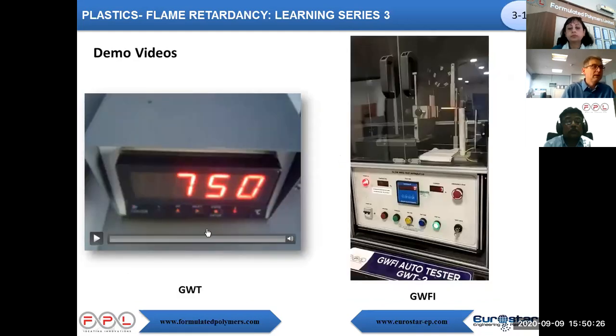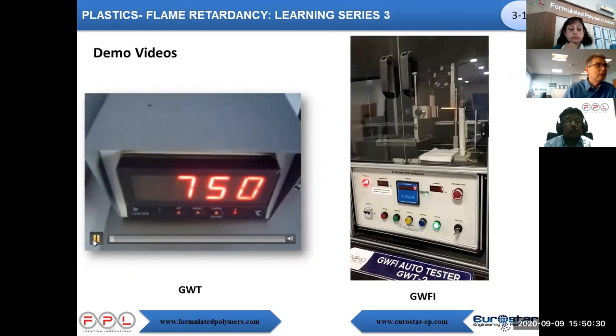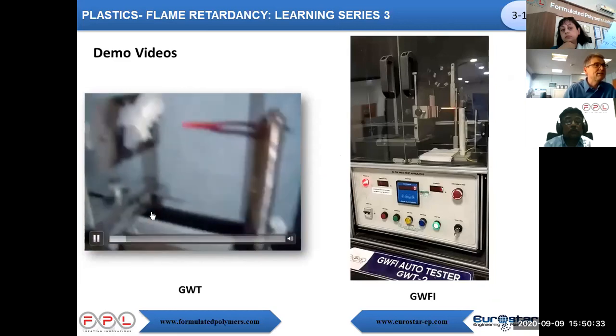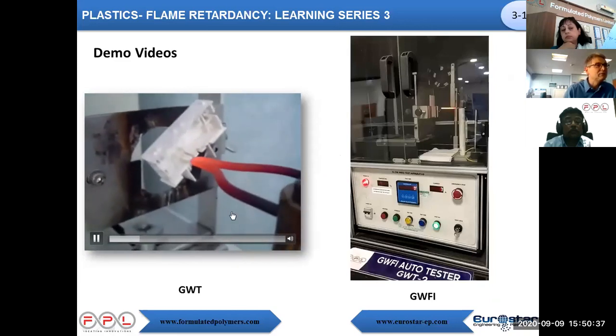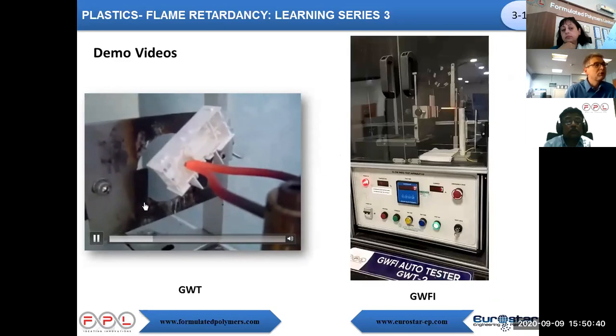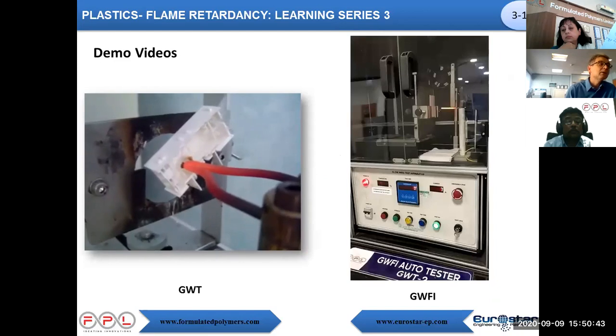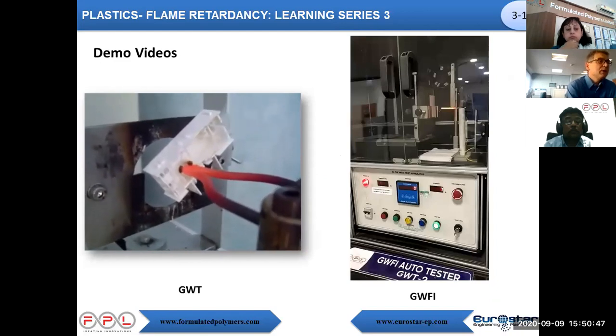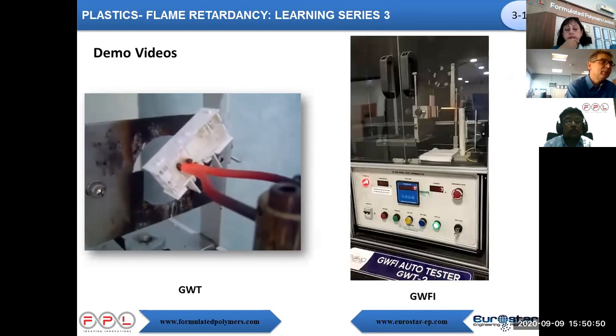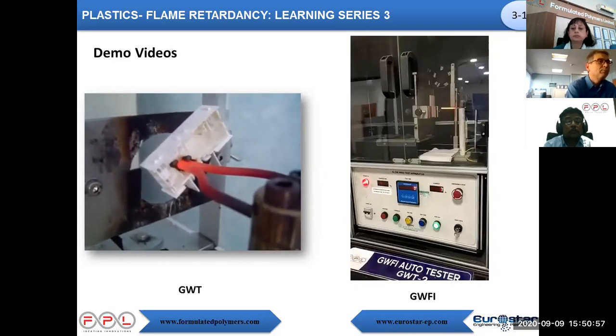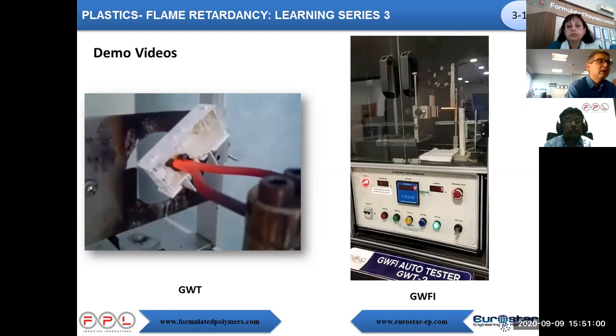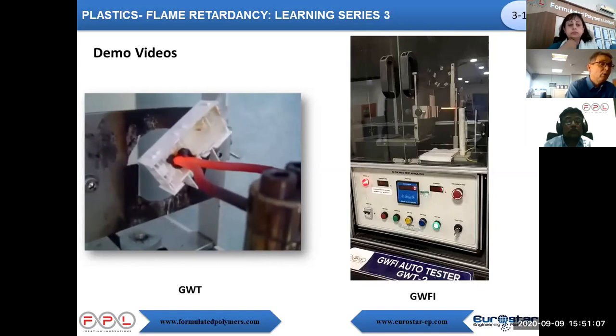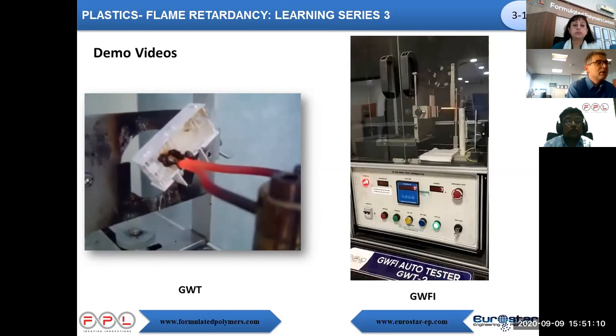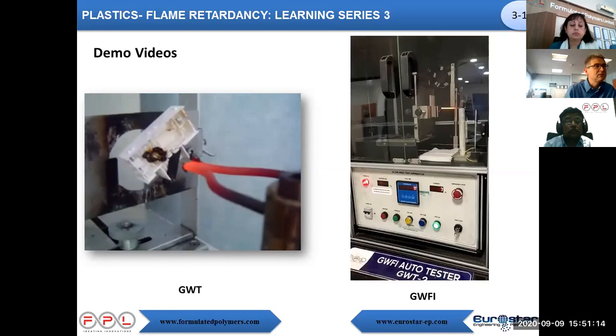Let's go now into real things. So the glow wire test, I'm launching the video. On this one, you see it's 750 degrees C. You see the wire automatically is applied to the part. Then the part touches, the material heats by conductivity. It's now overheating. You see the material is almost not burning, but charring. And in this case, it's quite well done because the charring takes place, the material fumes, but you cannot see the flame. To pass the test, you need to have a flame below 3 to 5 seconds. And in this case, there is no flame at all. So at the end of the 30 seconds, the wire is removed. And in this case, it really passed the test.